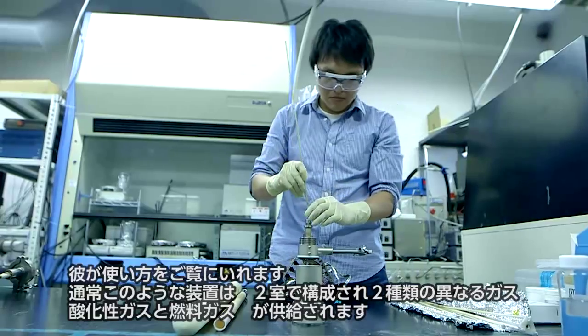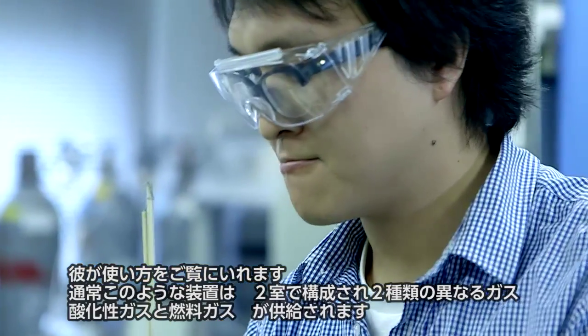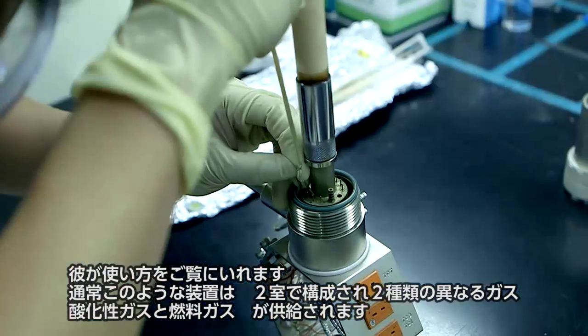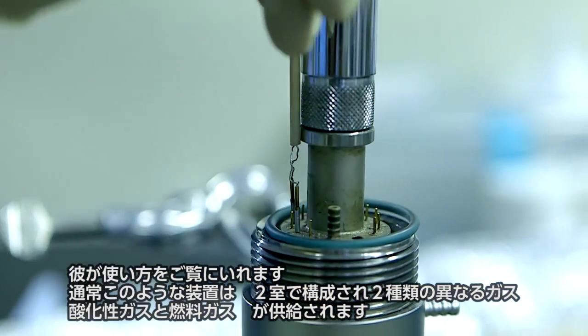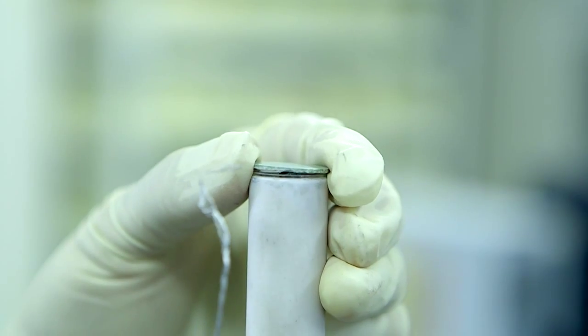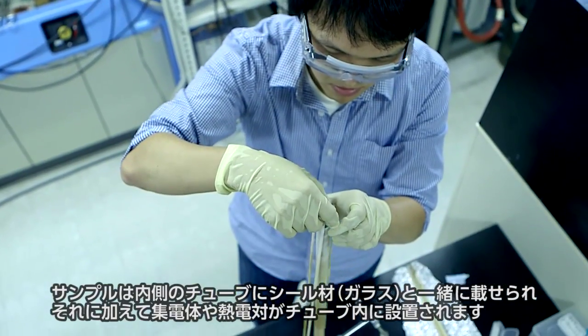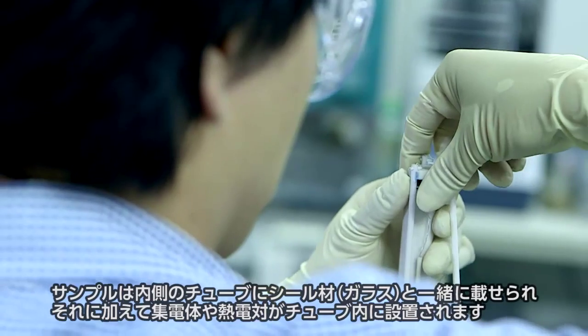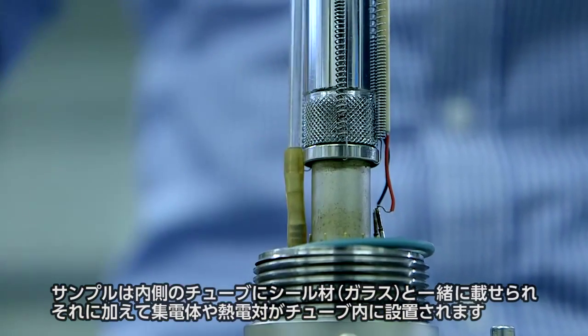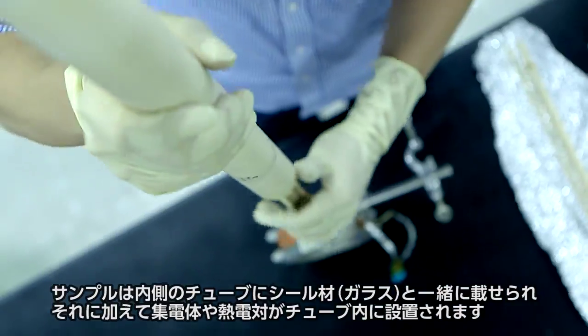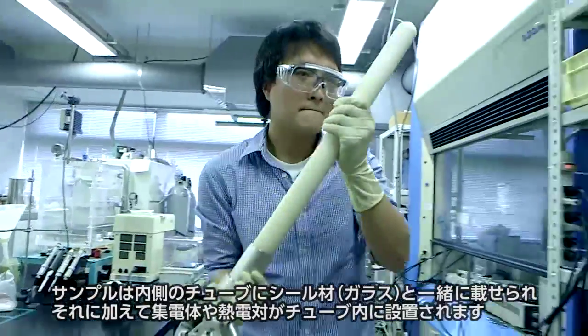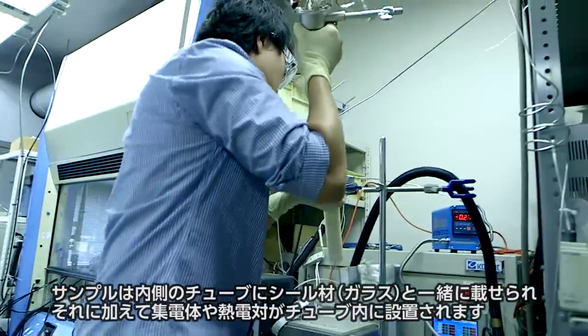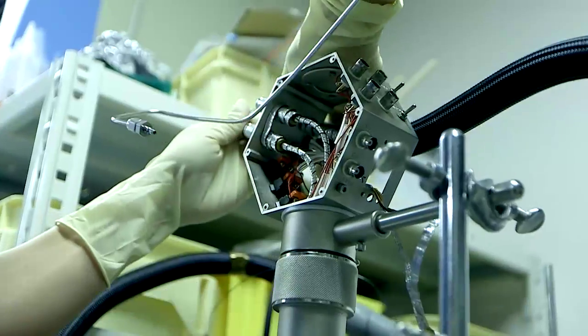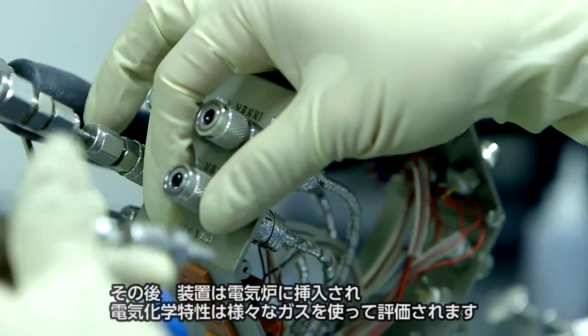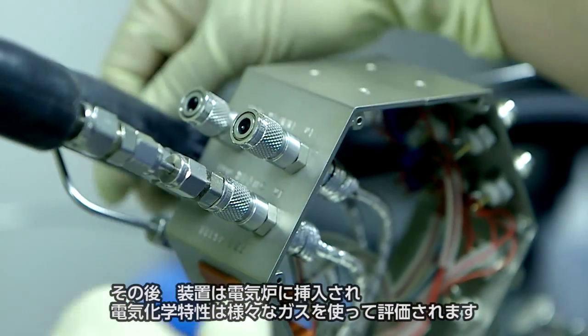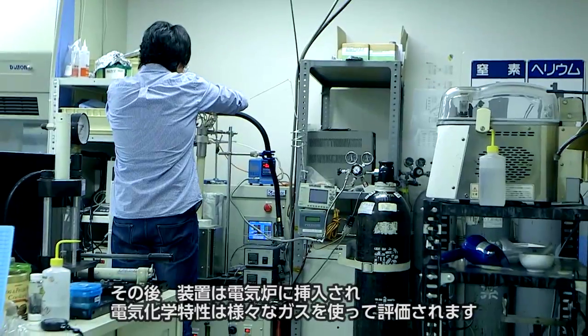Usually this kind of setup has two compartments to supply two different gases, that is, oxidant and fuel gases. The sample cell is mounted on the inner tube with the sealing material. This is glass. In addition to that, a current collector and thermocouples are also placed inside the tubes. Then the setup is put in the furnace, and the electrochemical performance is measured using various gases.